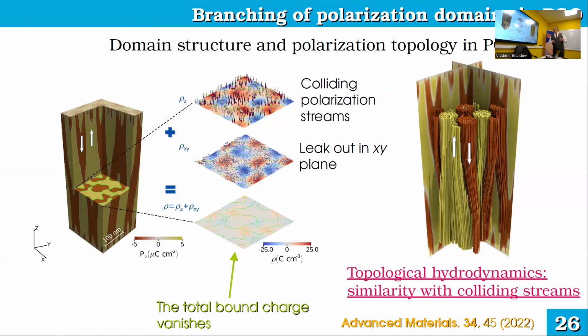And this in turn suggests that we have a divergence-free configuration of the polarization field in this case. And actually, it's in full agreement with topological hydrodynamics theory. So here you can see polarization lines of this field. To explain this behavior, we can draw a simple analogy. Consider two flows of water that encounter each other. To avoid shock formation, they just split in a V-shaped configuration. In our paper, we called it V-shaped scissoring, to avoid shock formation.